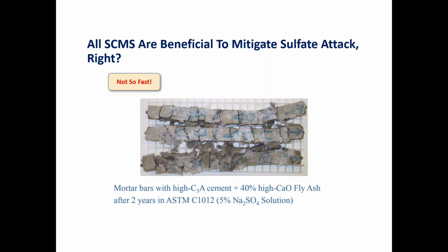Class F fly ash, you can add water to it, it does nothing. It needs certain things to activate it, like free lime and soluble alkali and things of that nature. So again, that's why that C1012 test is important, especially in an environment where even quality sources of Class F fly ash are becoming very irregular. The supply is. If you have a project where sulfate resistance is important, don't swap Class F ash for Class C ash. It's a good opportunity maybe for you to go back and say maybe we ought to look at the Class C fly ash, because you can use it as long as you demonstrate that it is suitable for mitigating sulfate attack.